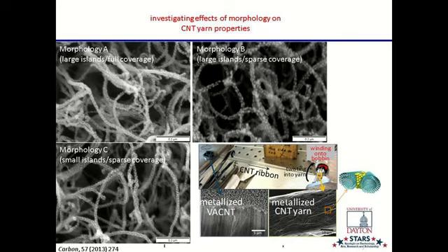And you can see this transparent black web. This is about a foot long. It's composed of these nanotubes. They pull off of the substrate, and they hold on to each other through these weak van der Waals forces. But you can pull them across. Remember, I said these nanotubes are 300 microns long, so this is a whole long line of carbon nanotubes making this foot-long line. And then I can wind it on one of these bobbins. Those are these silver things. There are 4 bobbins with different kinds of nanotube yarn on there.